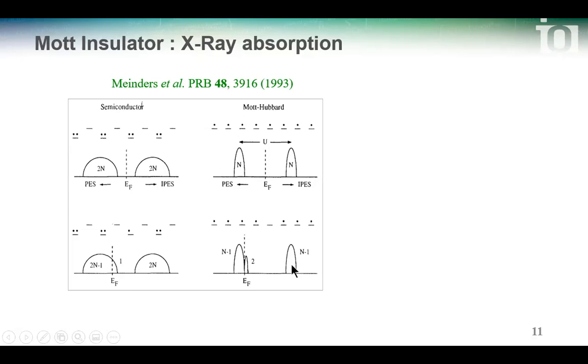In a Mott system, it's very different. Why? Because now you have one less electron here, you dope with holes. So there are n-1 states here. So you can add electrons on that will cost energy U on n-1 states, and you can remove on n-1 states. And you have created 2 states, so you're left with 2n states again. You have created 2 states near the Fermi level where you can put an electron up or down.